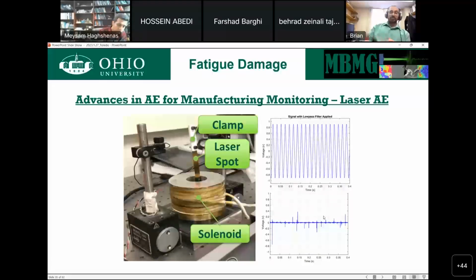That being said, I could at the same time be looking at acoustic emission. And what's unique about this is, in this top plot at this point, for this particular example I'm showing you, you cannot see a drop in amplitude under the applied load, which means as far as the global material sees, it's not damaged. But the acoustic emission is showing activity. What this tells us is there's microscale damage happening to this material that is not enough to yet affect the global properties. But eventually, as you see more acoustic emission, more of this happening, that's going to indicate more and more small scale damage that will eventually accumulate enough to finally affect the large scale behavior. And that's the power and the benefit of AE.